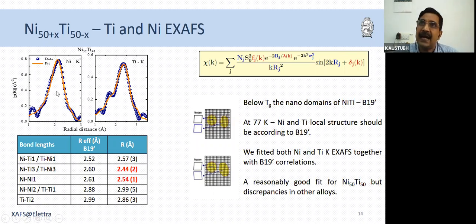So we started with that, and we could fit the titanium K-edge without any problem in all the alloys. But when fitting the nickel K-edge, except for the stoichiometric alloy, we had some problems. In fact, we could not fit the data. There were either unphysical parameters or something.